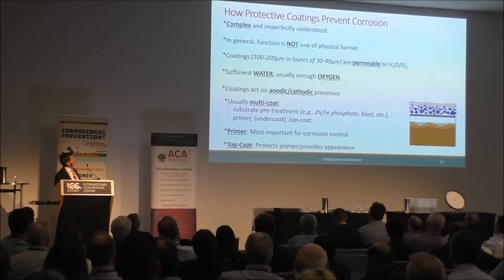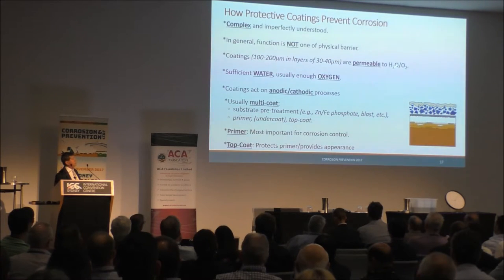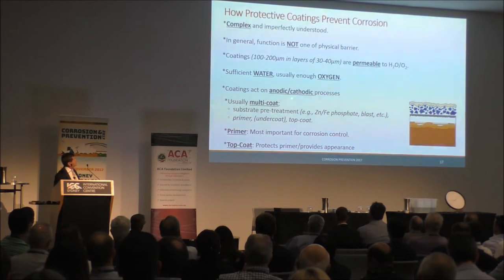But in general, the function of a paint is not just a physical barrier. Coatings, even quite thick, are really quite permeable to oxygen and water. There is pretty much always sufficient water that can get through the paint, and usually enough oxygen. So our coatings really have to be designed to act on these anodic processes.